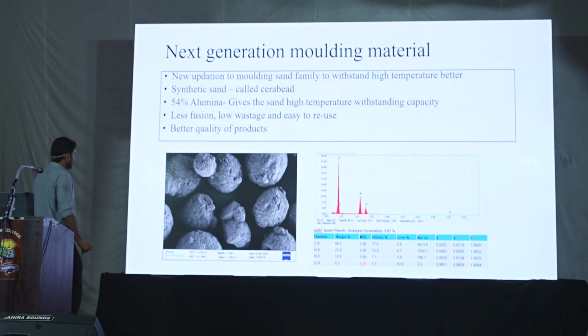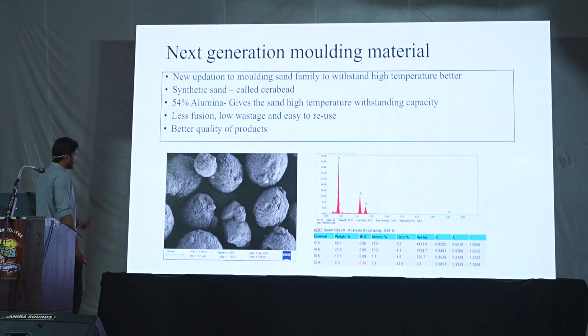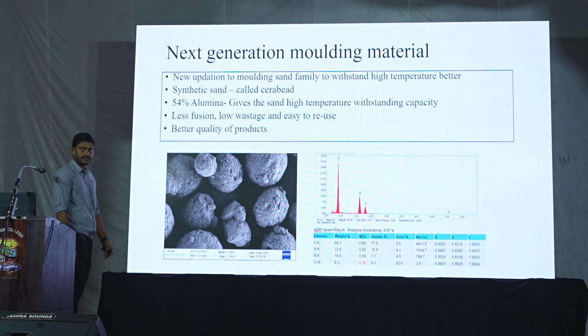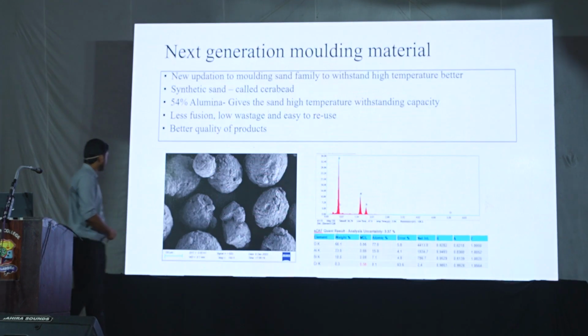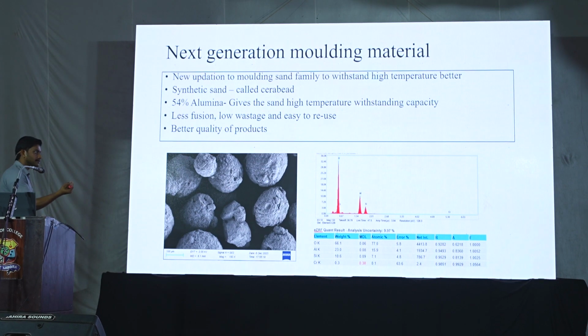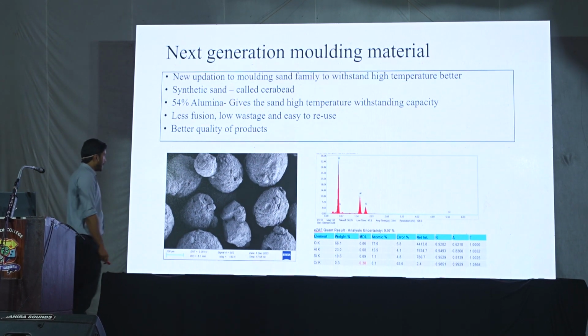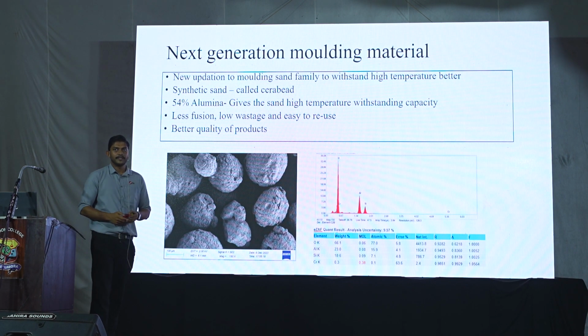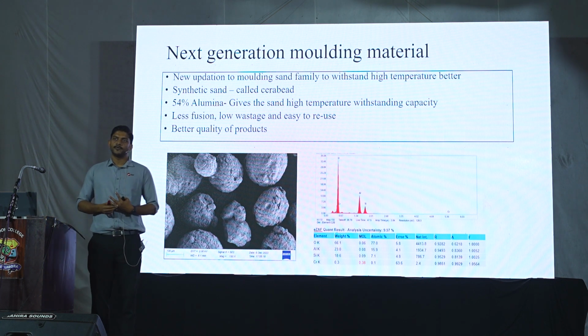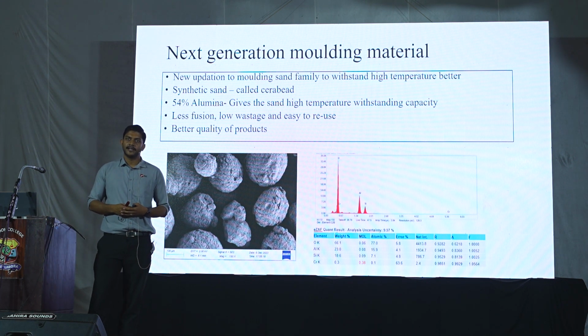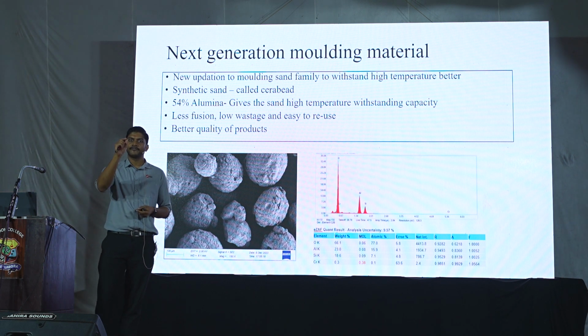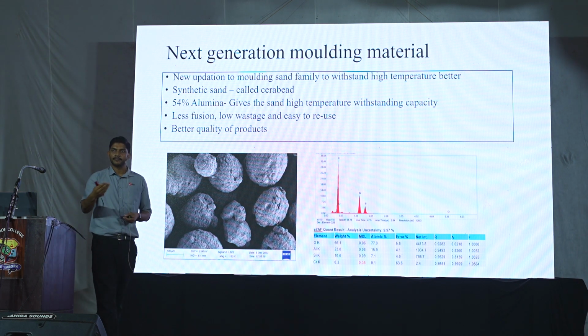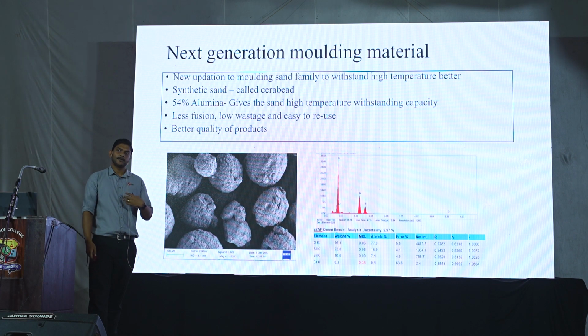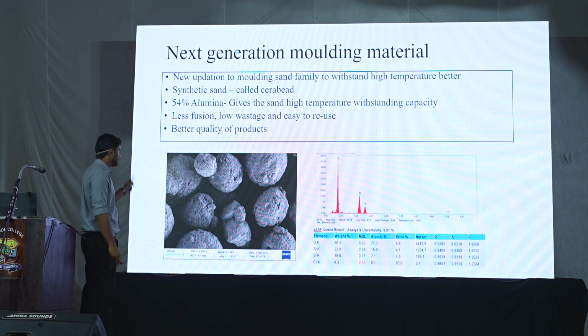So basically, you can see that most of the sand grains are almost spherical, and there are very few fines, as we call small particles, in this. Also, I said the temperature at which we pour the metal is 1600 degrees Celsius. Silica can fuse at that temperature, so a thin layer of sand will sometimes be fused onto the metal. That we can also avoid with this material.